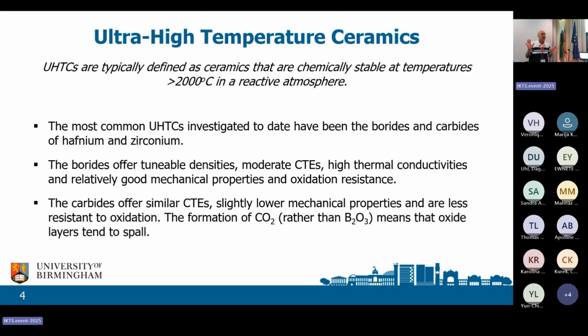Carbides have similar CTEs, generally slightly less good mechanical properties, and are generally less resistant to oxidation. But more crucially, when they oxidize they give off CO2 and CO, mainly CO2, rather than B2O3. B2O3 goes through a liquid phase before it becomes a gas, whereas CO2 goes straight to the gas. That is a large volume of gas, and it pushes off the oxide layer. The technical term is spalling. Once that's pushed off, you've got fresh surface for attack. So the boride is more protective.